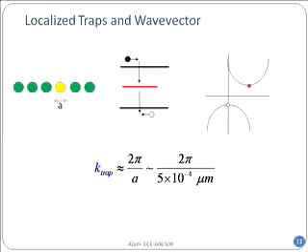And what it helps is that the trap level is right there, shown here in the energy band diagram as a small red line. And what the trap does, it provides a lot of wave vector so that the electron from the bottom of the conduction band can move to the trap, right? And once it is there, it is perfectly aligned with the valence band. And so now when the right hole comes in, it just drops in. And then in the process, it recombines. So that is how the indirect band gap recombination occurs.